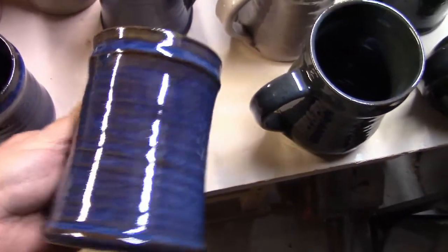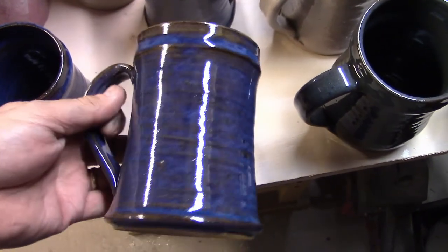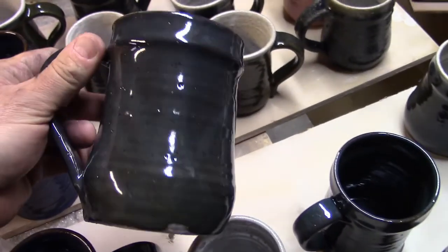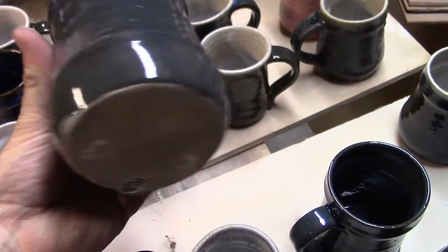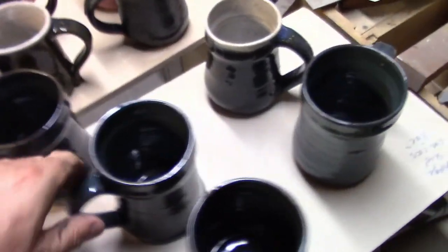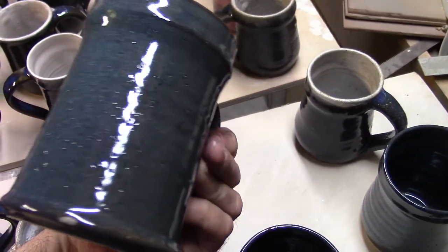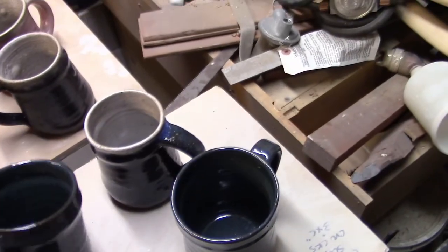Another tankard - this is just straight floating blue in and out, not horrible but has a pinhole. And this Caribbean sea green again has pinholes plus it's dark. I know why: A, it's over-fired, and B, this kiln went into reduction and these are all oxidation glazes, causing pinholes. Learning curve.